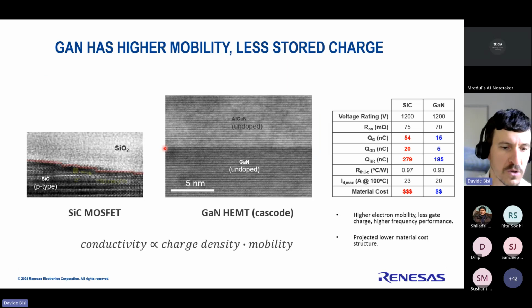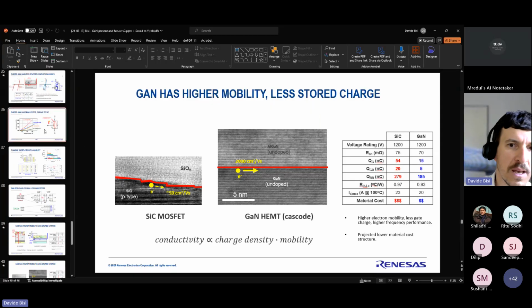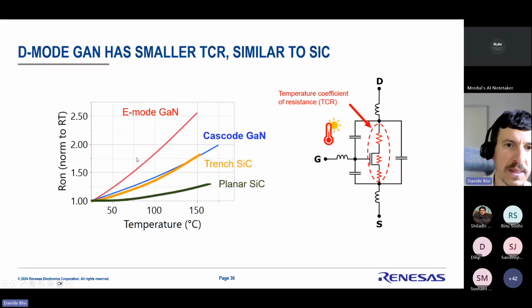Regarding the thermal, your question about the thermal, I had a slide on it. This one is the temperature coefficient for resistance. You can see how the resistance increases as a function of temperature. GaN, for some reason, which is not clear to me yet, from 25 Celsius to 150 Celsius, the resistance goes up 2.6 times. With cascode, we see the resistance goes up 1.7, 1.8 times. And you can see that now cascode is the same as the trench silicon carbide.